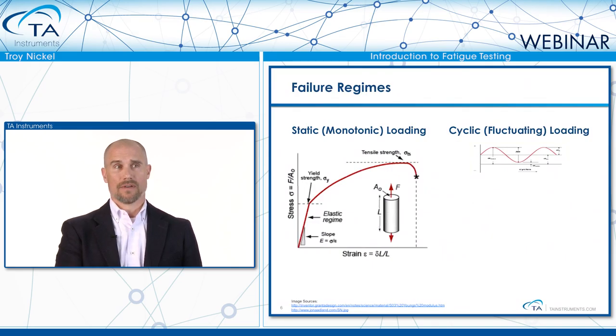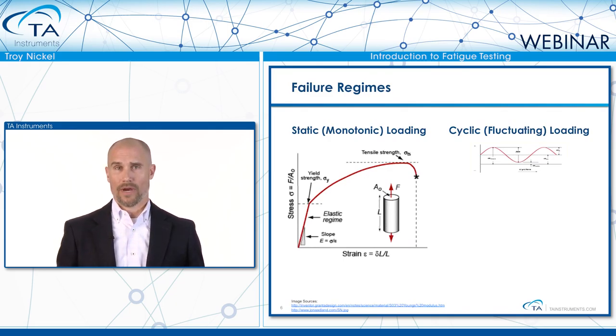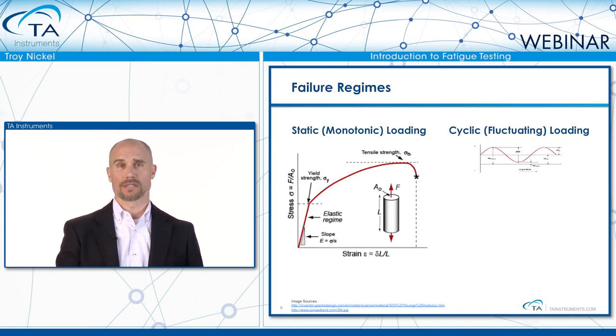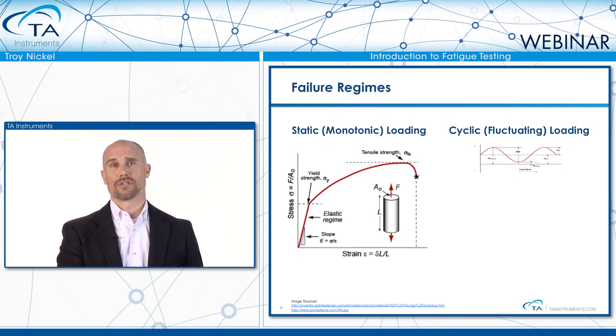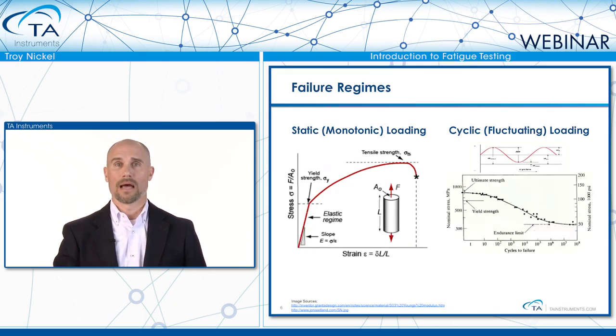Let's talk about these different regimes. In the static case, we take a material and pull it to failure once — we get a curve with an elastic region transitioning into a plastic region where the material deforms permanently, reaching maximum strength and eventually failing. But thinking about Wöhler and the bridge incidents, we also need to understand repeated or fluctuating loading. You can run a load profile that repeats stress cyclically and observe how materials fail there.